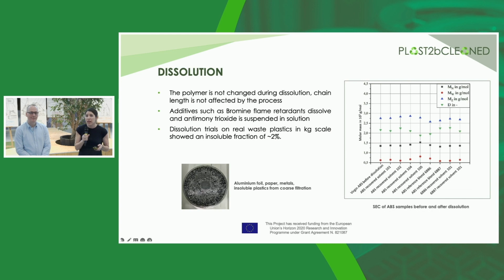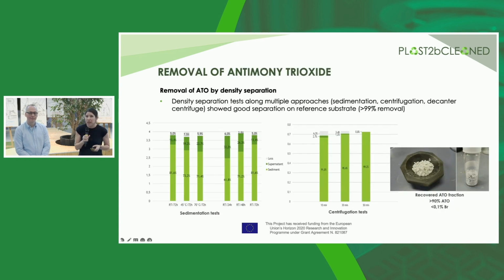In this process, bromine flame retardant and also antimony trioxide were suspended in the solutions, and we have approximately 2% of insoluble fraction. For removal of antimony trioxide, we tested several routes. So there are multiple approaches that have their benefits and drawbacks. So we can rely on sedimentation, centrifugation, even decanter centrifuge, and they showed good separation when tested on a reference substrate.